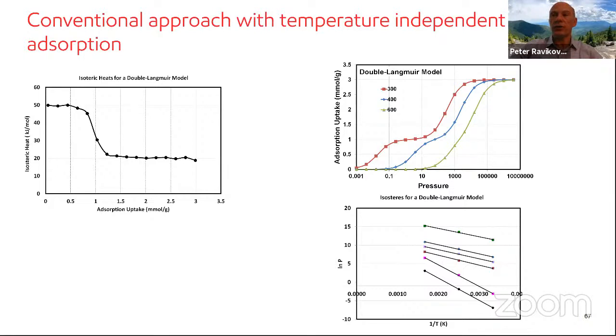Another indication of phase transition is often a step on the isotherm. It doesn't necessarily mean that you have a phase transition, but more often than not, for microporous materials, if you have adsorption and you have a sharp step on the adsorption isotherm, you should suspect that something similar to a transition is occurring. These are good indications of a possible phase transition.